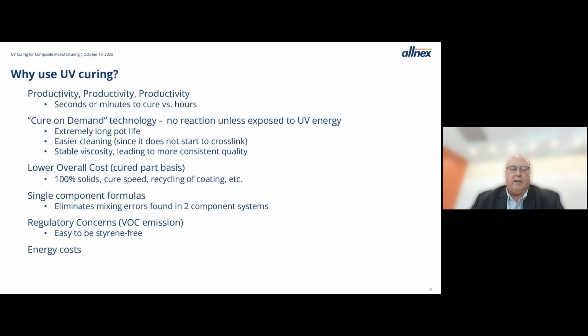It's also a cure-on-demand technology, and I think this offers a lot of advantage as well. There's no reaction in a UV system unless it's exposed to UV energy. In thermally cured systems, once they're mixed, even at room temperature, there's thermal energy available, so they start reacting, and that means that there is a definite pot life, and it's usually reasonably short. With UV, if you don't expose your formulation to UV energy, it's got an extremely long shelf life, extremely long pot life. So it'll last a year or more in a drum fully formulated.